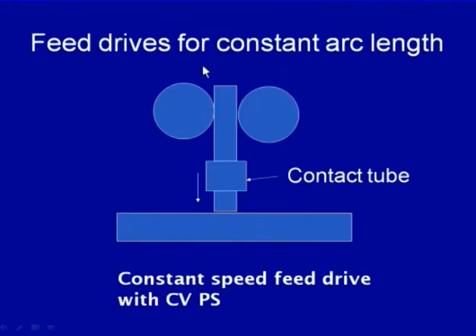So, here we see that there are two types of feed drive systems which are used for maintaining the arc length. One is used in association with the constant voltage type of power source. In these conditions, the constant speed feed drive system is used, so that it helps to maintain the arc gap. But this approach is mainly used for welding processes when a small diameter electrode is used with a large electrode extension, and the material is of reasonably high electrical resistivity, so that the I square R component of the melting rate is high enough to regulate the melting rate. Under those conditions, the constant feed drive system in association with the constant voltage type of power source helps to maintain the arc length.